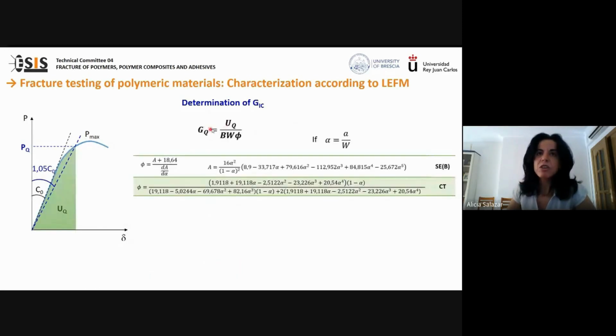For determination of G1C, we determine a conditional value, GQ, with this expression, where UQ is the energy computed as the area under the load displacement curve up to the very same load point used for K1C determination.